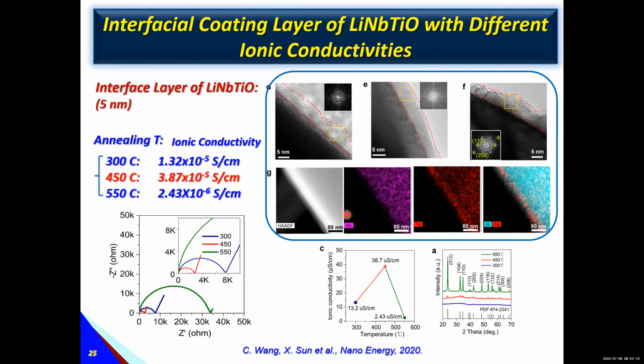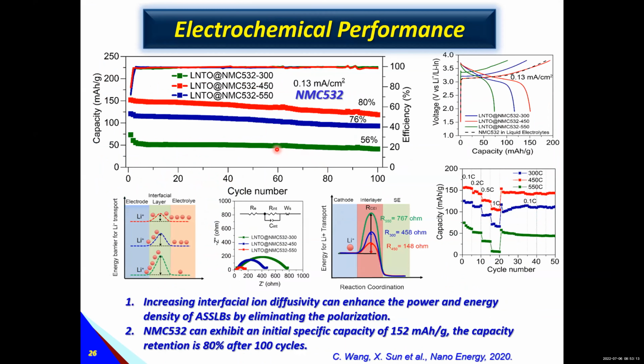So after we tested performance, interestingly, we found a big difference. With the highest ionic conductivity at the interface, we see that it maintains much higher capacity. With the lower ionic conductivity, its capacity is much lower. So that indicates this barrier, lithium transport at the interface, is so important, even for rate capability. So from this study, we know that we do need really good ionic conductivity at the interface.